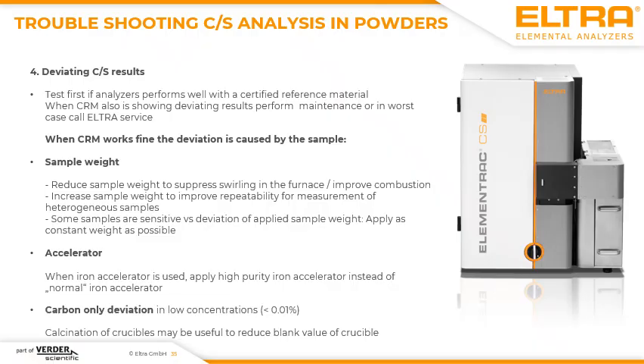Also make sure when you're getting deviating results that the correct accelerator is applied. When you have samples, for example, like ferrotitanium, you always have to apply iron accelerator in addition. Otherwise, you would get no stable result because the sample is not combusted completely. When you have very low concentrations of carbon and sulfur, make sure that you are using a premium accelerator because there the deviation of carbon and sulfur is very, very low.